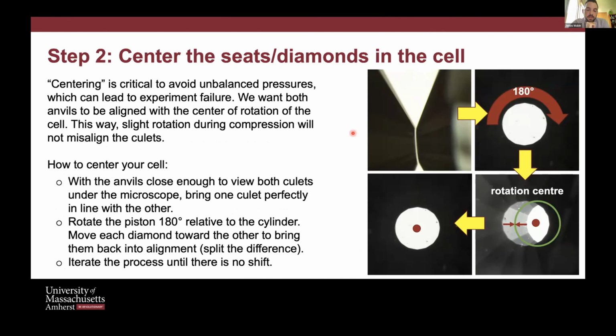Some groups don't do it, and that certainly will come back and bite you sometimes, especially if your cell has some rotation during compression. Make the assumption that as you bring the cell together, the piston into the cylinder or whatever design you have, that there might be some rotation. If your diamonds are not aligned on what we call the center of compression, or center of rotation, sorry, then that rotation can induce misalignment of the culets, and that can cause all kinds of problems. So the first step you should do, if you've inherited a cell that someone says is centered, you should check it. And this is the way that you would check it.